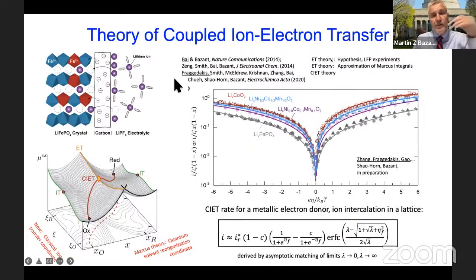the work shown here. So I have a paper of 2014, actually an experimental paper, which was the first to point out that intercalation may actually be limited by electron transfers. So as shown in this picture in the upper left for lithium iron phosphate, it turns out lithium iron phosphate is actually an electron insulator. So it doesn't like electrons. So in order to insert your lithium ion, you need a compensating charge.